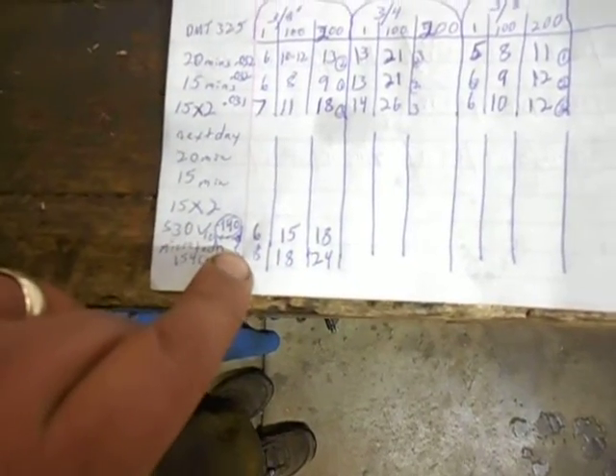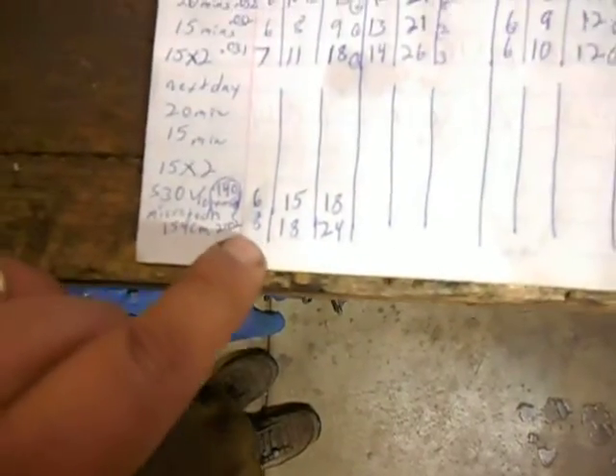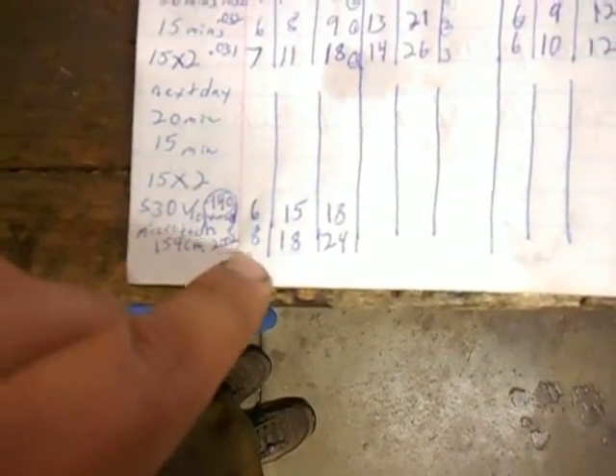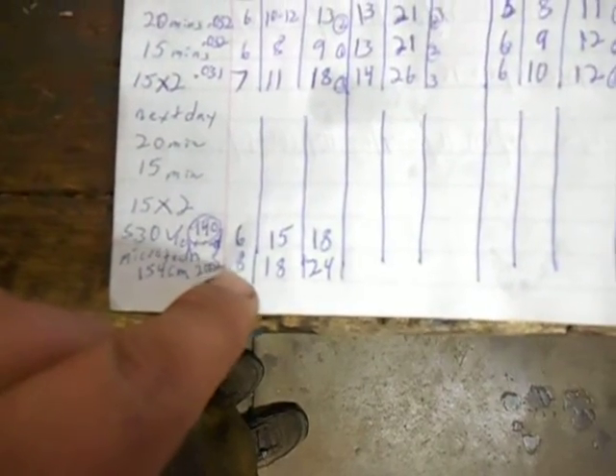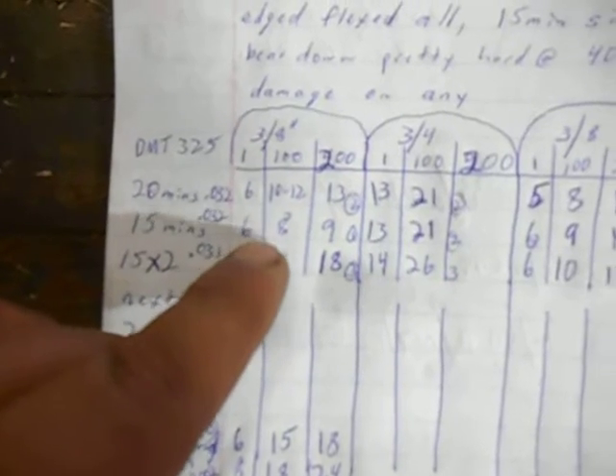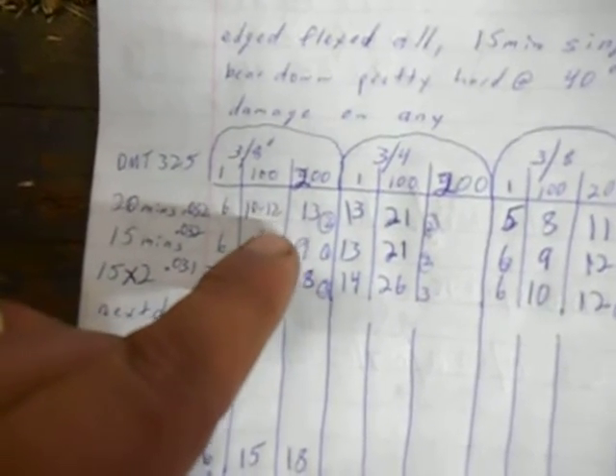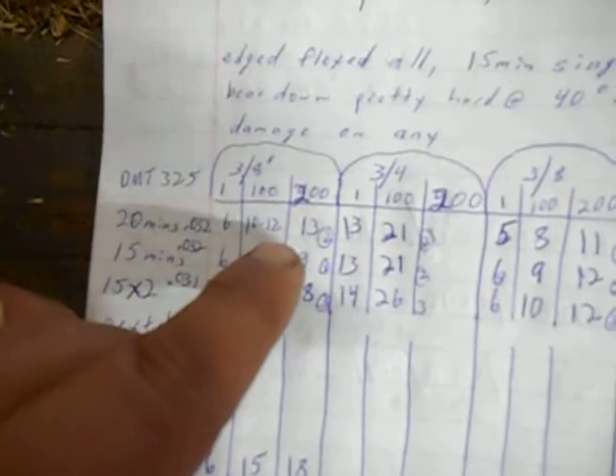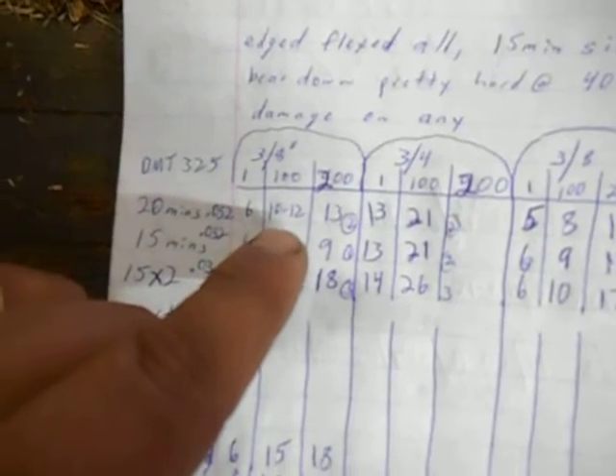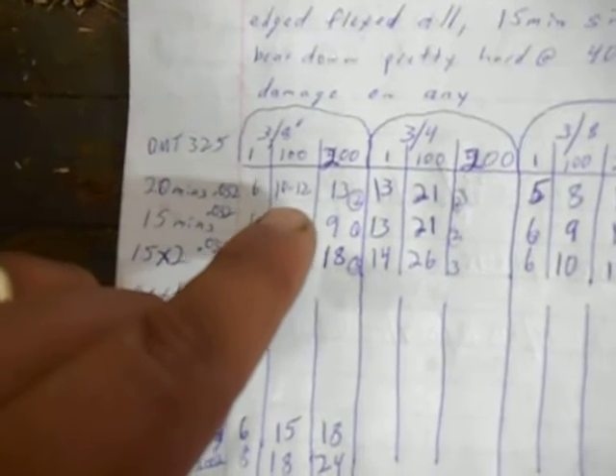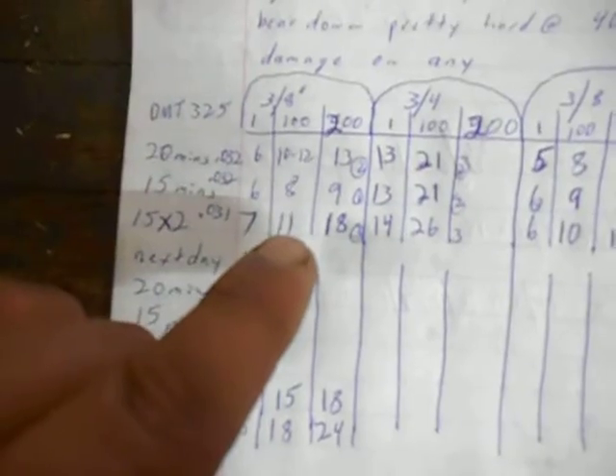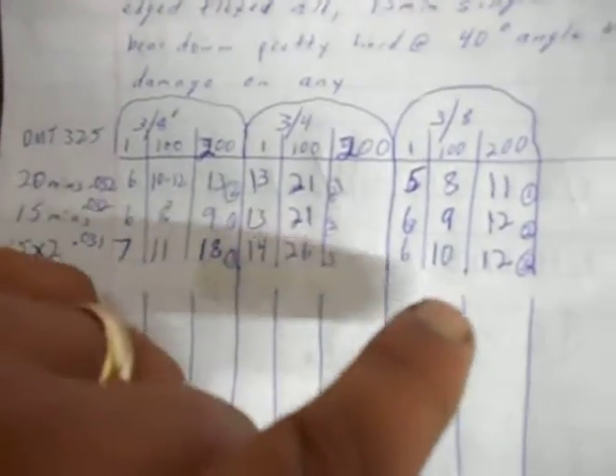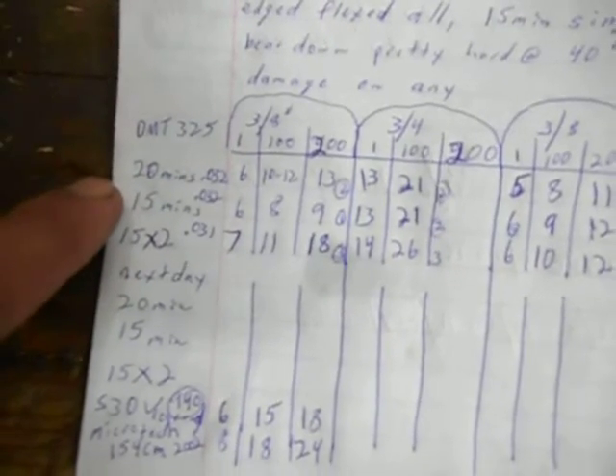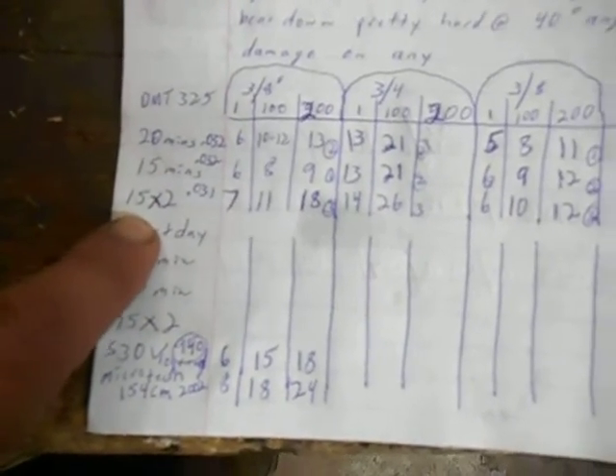that's been reground. So these blades, that first number is the amount of force to complete the first cut, the second number is the 100th cut, and the third number is the 200th cut. So you can see they cut pretty well. This one right here, not really sure what happened there, if I didn't get the edge sharp enough to begin with, or if I left a little bit of a burr on it, or maybe I just hit a really hard section of rope. You never can tell. But basically, according to these three runs, the 20-minute and the 15-minute ones did better than the double quenched ones.